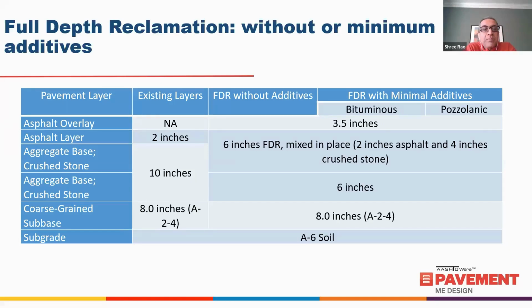So here are some design examples. And again, to compare this, if you design a pavement with the 2-inch asphalt layer and 10-inch, this first set is for full depth reclamation without or just a minimum amount of additives, which is bituminous or cementitious. You have an existing layer modeled as 2 inches over 10-inch crushed stone aggregate, and then 8 inches of coarse grain subbase, and then A6 soil subgrade. And here we have this model with a 3.5-inch asphalt overlay, 6 inches full depth reclamation, and 6 inches of crushed stone.